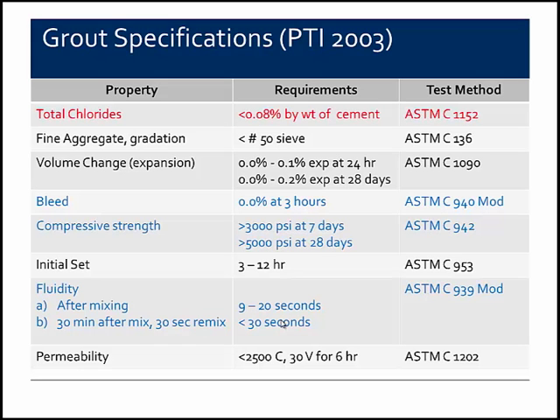Once again, from the PTI 2003 specifications, these are some of the grout properties that were in that specification. The different colors I put on here indicate various tests that are run in the field or during trial batching, and to explain the differences. So total chlorides is in red, and that's a very low percentage, 0.08% by weight of cement. That test is only run, at least in the 2003 specifications, when the initial trial batch was made. There was no requirement in the specifications at the time for subsequent testing for chlorides, and that's an issue that the 2012 specs are going to address.